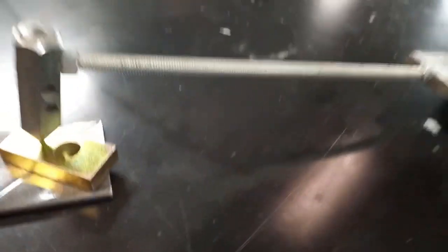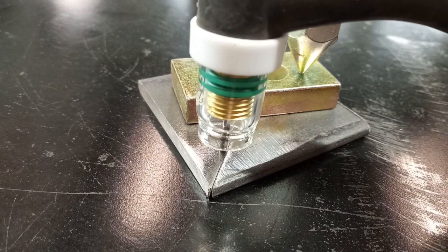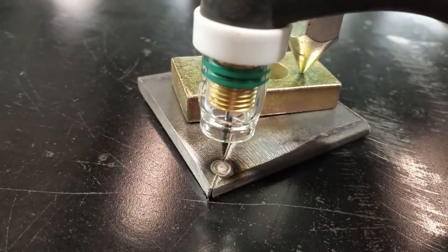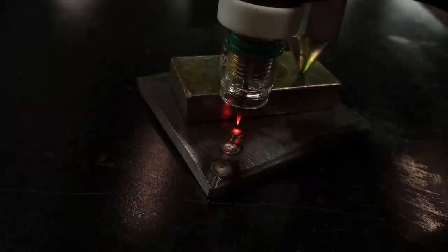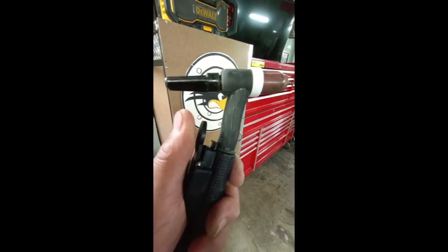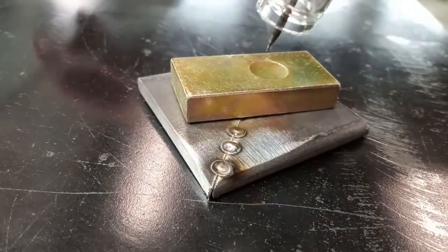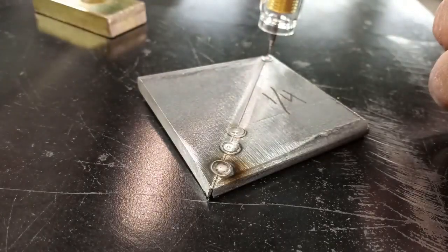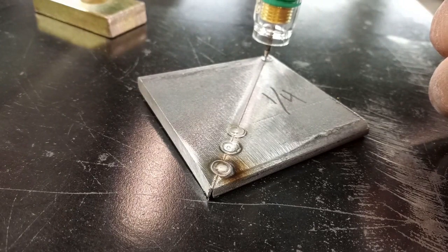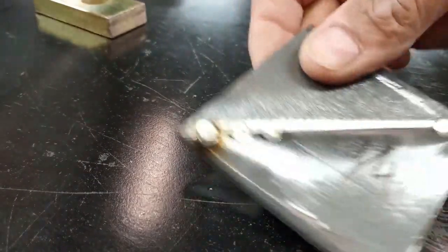There are two key things that you have to do in order to make this work, but once you get it dialed in, it works well. Okay, first up, first key is whether you're using a finger switch or a foot pedal, the trick is on/off as quickly as possible. We don't ramp up or ramp down, it's just hit it on/off. That's the first key. You can kind of see how fast we're going, initiating the arc and letting off. And that's the result.